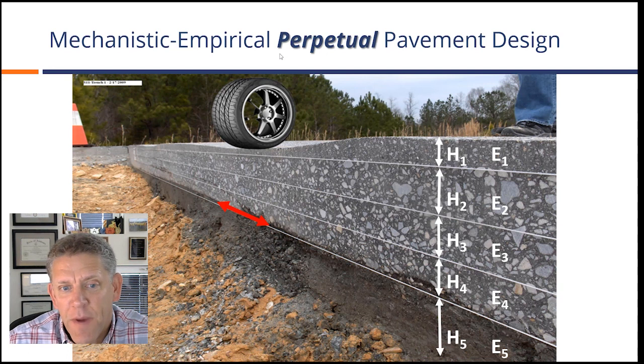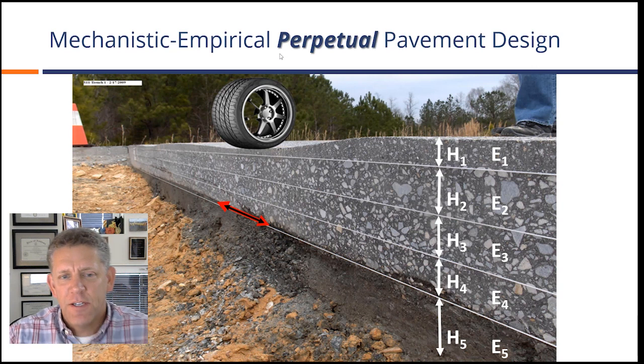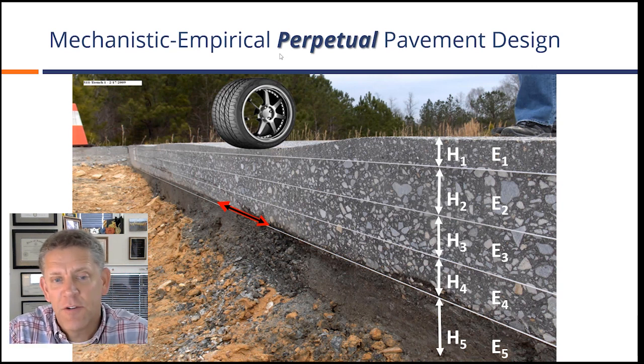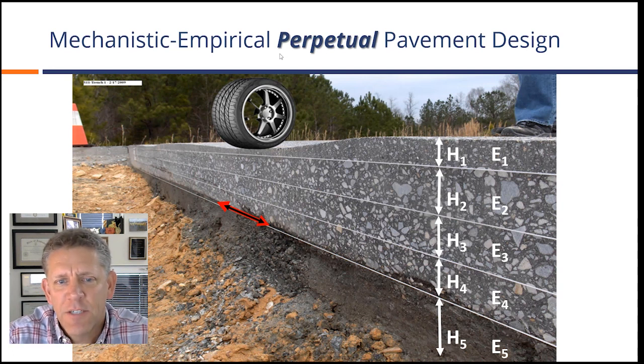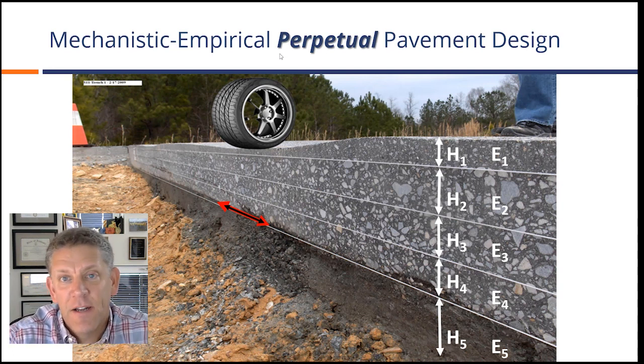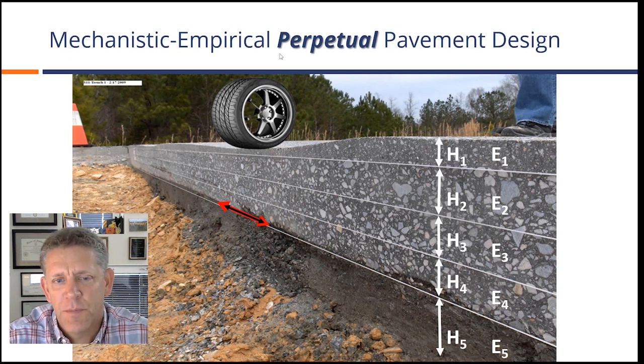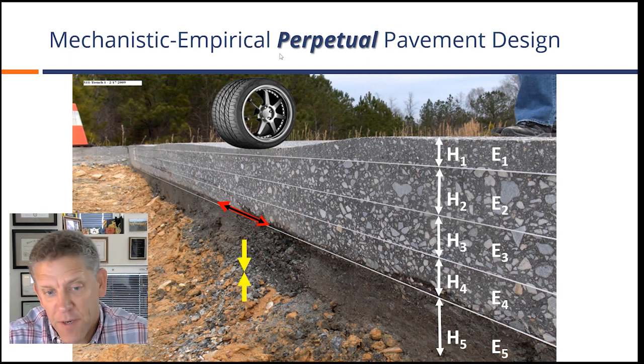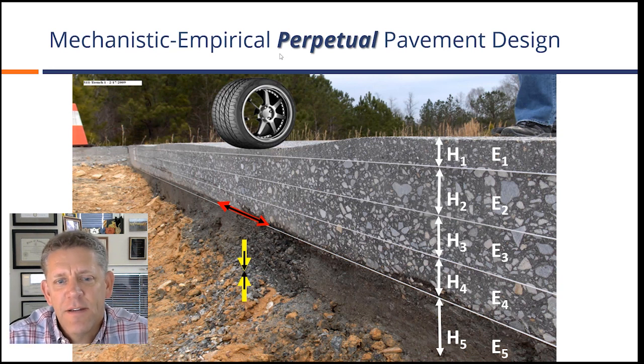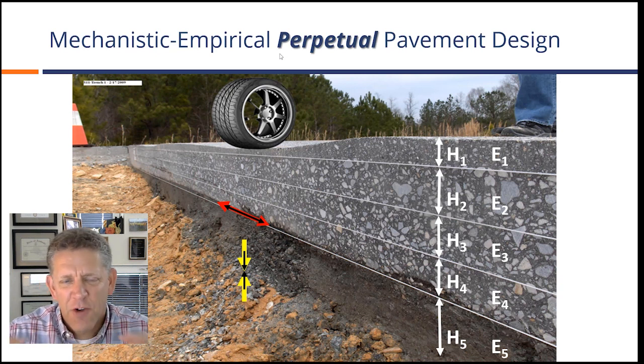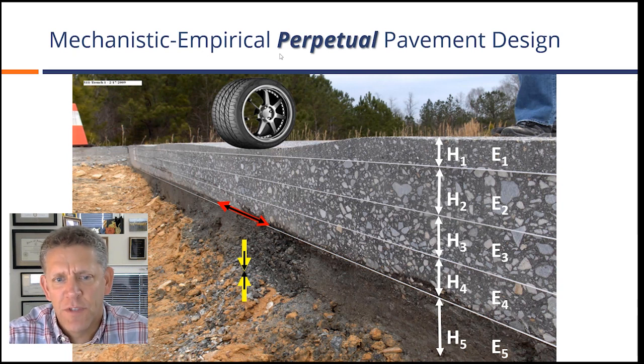We calculate pavement responses, but now instead of making an empirical prediction of performance, we're trying to limit how much strain we see to some critical level. We call it the threshold strain or the endurance limit. And if we keep the strain level that we see in the pavement below the endurance limit, there will never be enough tension at the bottom of the asphalt to initiate or propagate a crack to the surface. That's where we want to be in terms of perpetual design. And likewise, we can think about deeper in the structure and limiting how much strain we see there to some endurance limit, so we do not see those types of distresses at the top of the pavement. So characterizing that endurance limit is very important in perpetual design.